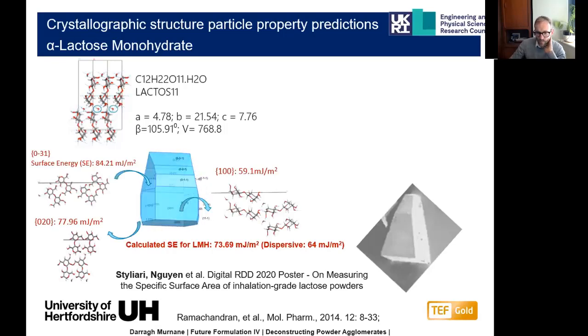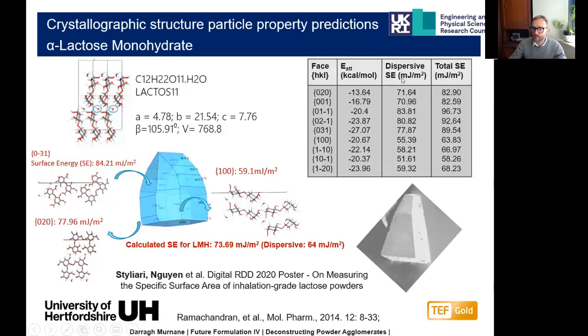And you can see from this work, which we've again published in Digital RDD, being able to index individual crystal faces and characterize the surface energy of those individual crystal faces. So from this, we're able to identify what the surface energies are between individual crystal faces, for example, and we were able to calculate out adhesion force measurements, similar to as we published previously in 2014 in this work before the project started. We're able to work out attachment forces, dispersive surface energies, and total surface energies across the multiple faces of the surface. So that means we can now work out the binding forces or the adhesion forces of our drug onto each individual crystal face. And if we know which crystal faces are presenting in our powder blend, then we're able to understand the detachment force that's going to be necessary during aerosolization.